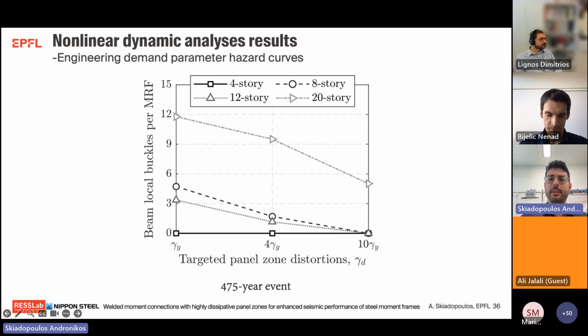Finally, engineering demand parameters for the number of beam local buckles were also developed. What we see is that conventionally designed moment resisting frames experience 3 to 12 beam local buckles per MRF for the design basis event, contrary to practically 0 once we allow for inelastic deformations within the panel zone. It should be noted in this case that fracture was not evident in the design basis event as well as the maximum considered earthquake event. This is particularly important from a structural repairability point of view, since beam local buckling is delayed once we allow the panel zone to participate in the earthquake energy dissipation.